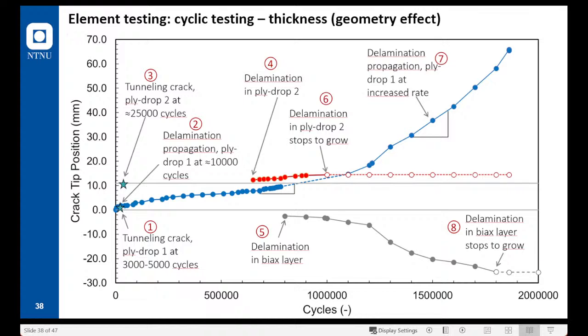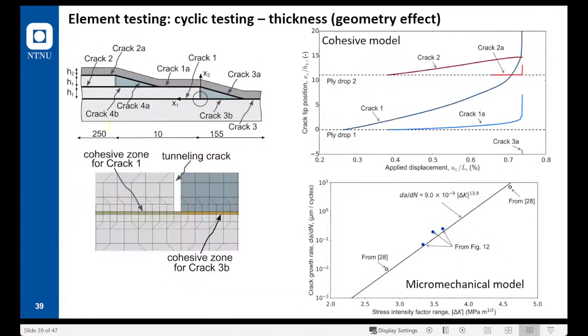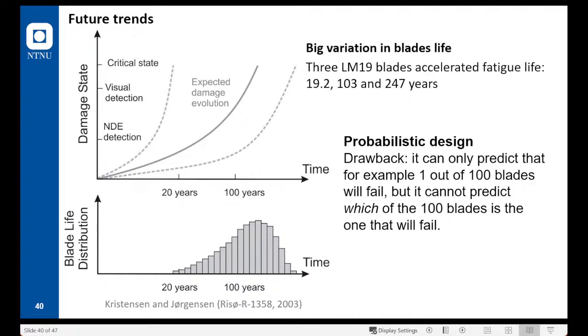For example, the red dots show a crack that starts, but then it stops growing. On the other hand, the blue line shows a crack that at some point grows much faster than all the other cracks. Through these experiments, we can understand which is the critical point of our structure, and we can further optimize this point. I can skip this slide.